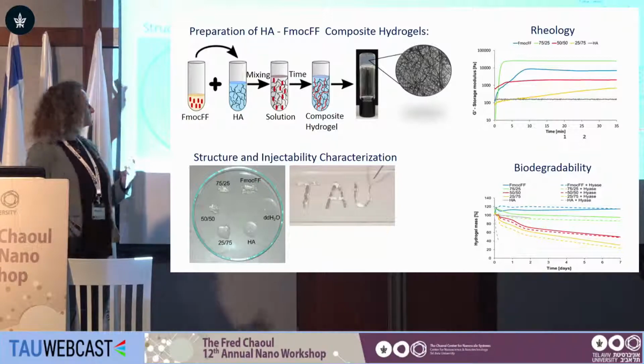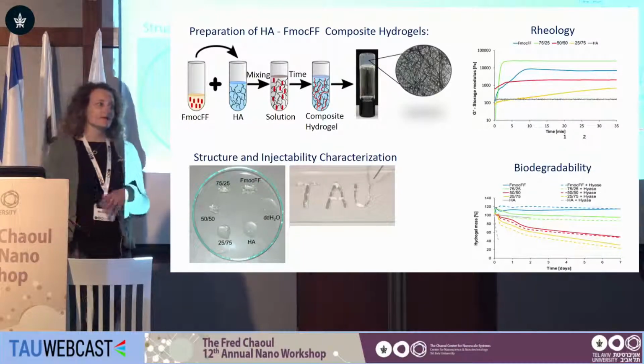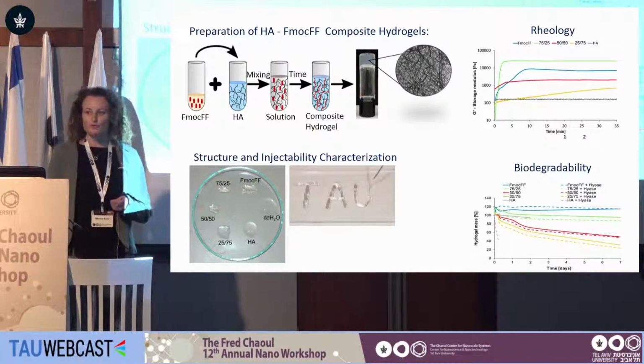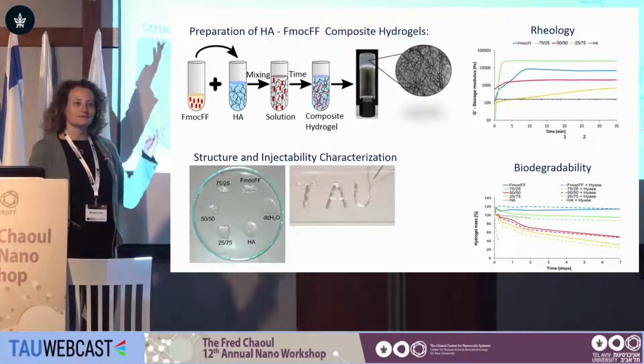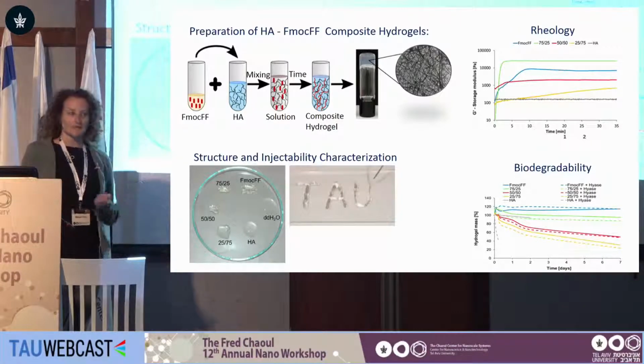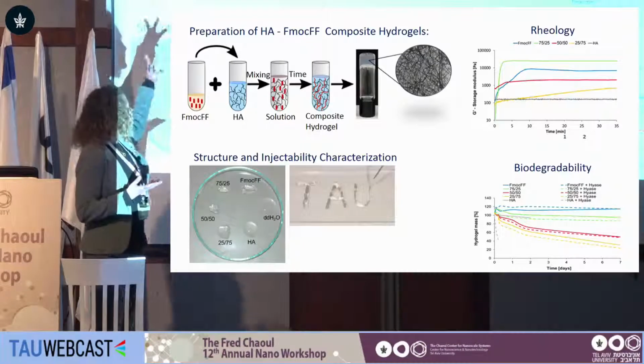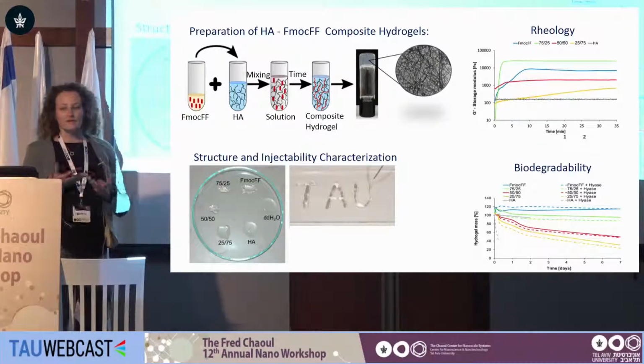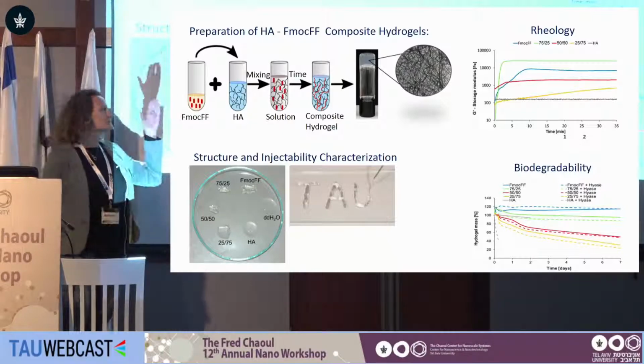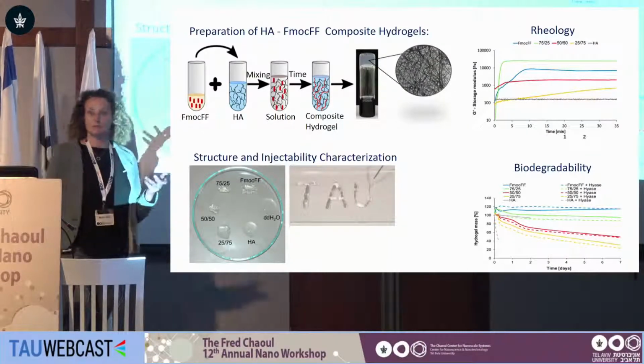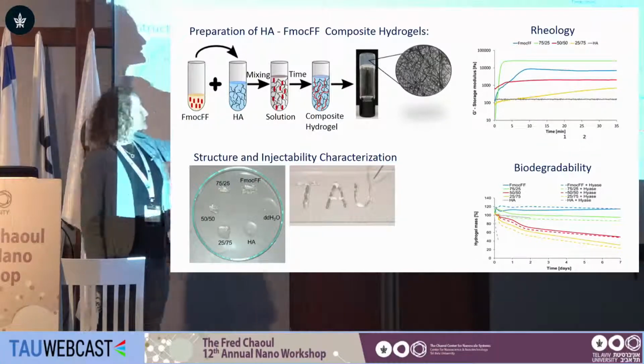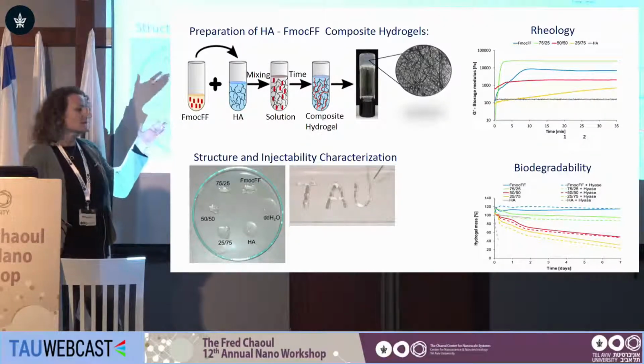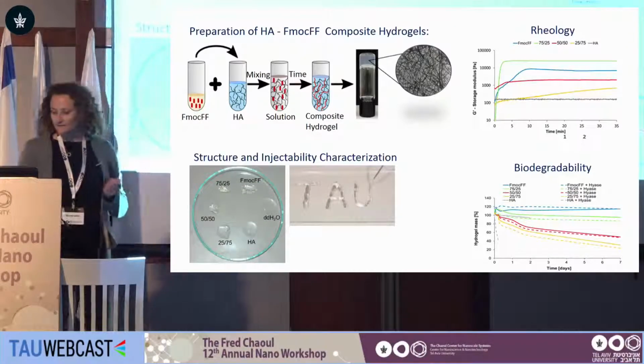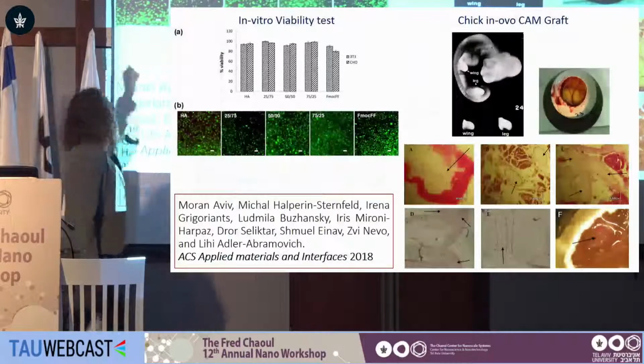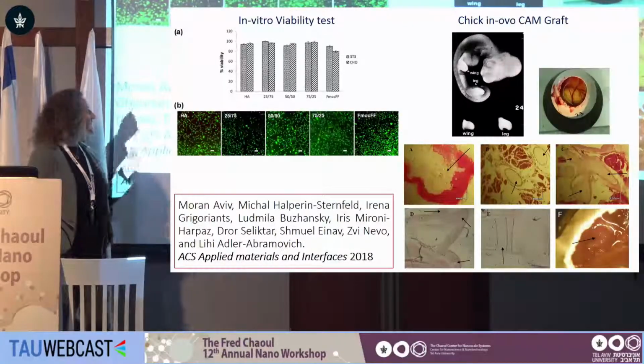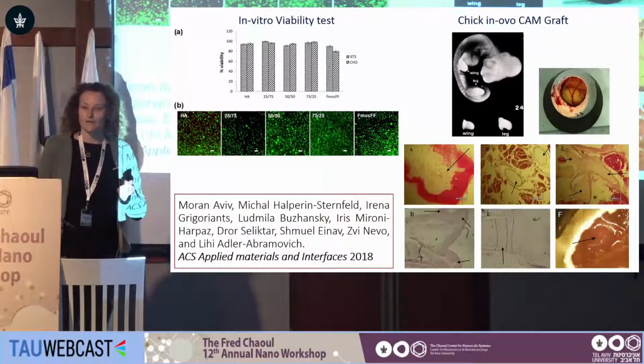One way to strengthen HA is to cross-link it, and we provide a different approach of reinforcing the HA with the FMOC diphenylalanine peptide. So we mix these two compounds, HA and FMOC-FF, together to form a homogeneous fibrous network, transparent and injectable composite hydrogels. These hydrogels represent notable mechanical features with improved stability to enzymatic degradation. In vitro viability tests with a few types of cells show very good biocompatibility features.